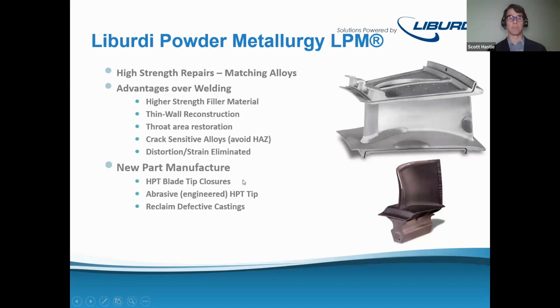That's on HPT blade tip closures, where they're concerned about the stresses caused by local welding. We've also done abrasive engineered HPT tips that have abrasive that will cut into a seal and provide better clearance control. We developed that with an OEM and created the equipment to do that process. And then more recently, we've been involved in reclaiming defective castings prior to getting machined into the final component, to replace some damaged or missing material.